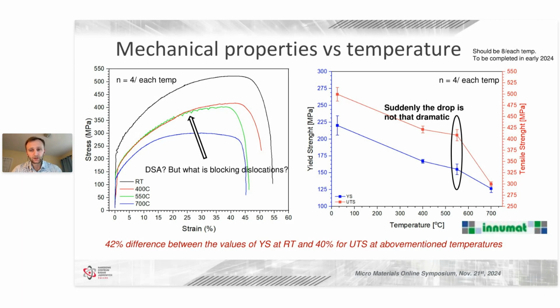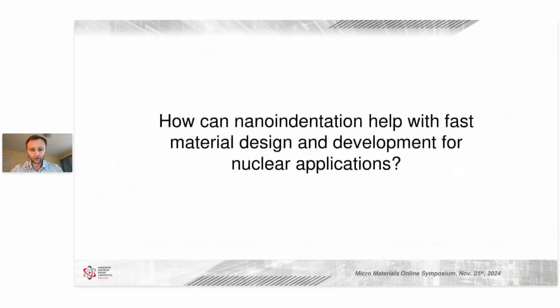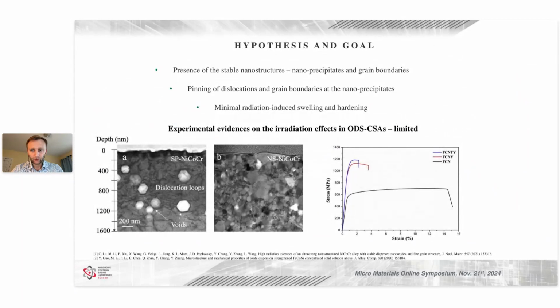But this demonstrates that nano indentation in the nanoscale can be quite easily compared to the macro scale measurements. And to conclude with radiation damage resistant studies, I want to bring your attention to two examples of high entropy alloys we are developing. We hypothesize that when we put a lot of stable nanostructures in the form of nanoprecipitates and small grains, we will create a big density of grain boundaries that will pin dislocations and consume both vacancies and interstitials produced